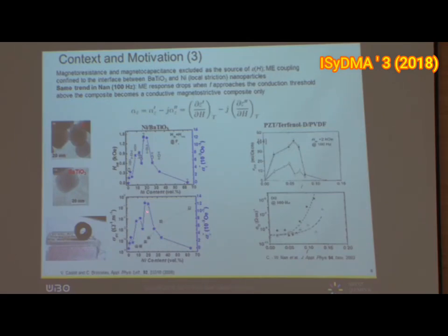What is also important to notice in this data is that the peak in the coupling is very well correlated to the percolation threshold of the system, because nickel is very conductive compared to barium titanate. This result is exactly what some people measured a few years ago using thin film geometry with PZT and Terfenol, which is piezoelectric, and the magnetoelectric coupling has exactly the same shape with the peak, also correlated to percolation threshold.